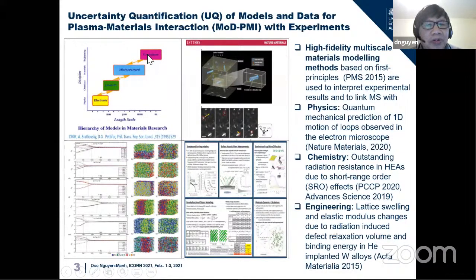Going to the engineering side, I'm showing a summary of the DFT prediction on the elastic modulus change under irradiation. You cannot see it here, but you can see in the Acta Materialia paper that we predicted about a 2% reduction in the elastic moduli for tungsten under helium implantation. It was detected experimentally, and it perfectly shows that the ab initio calculation can go on to look at engineering problems.